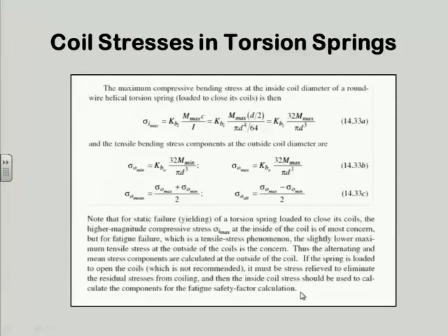So it's saying if, for whatever reason, I want to load this opening the coils, I better get rid of those residual stresses. And the way to do that is I put it in an oven and bring it up to a magic temperature, which is pretty hot, and then I let it cool slowly. And so I let those molecules all rearrange themselves in there and get rid of all those residual stresses. That's called stress relieving.